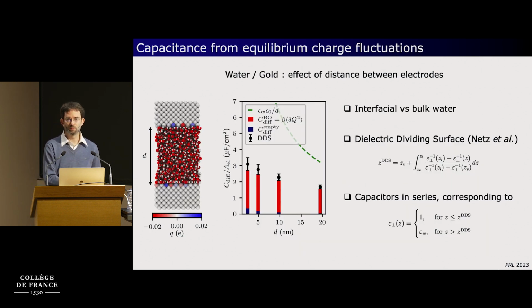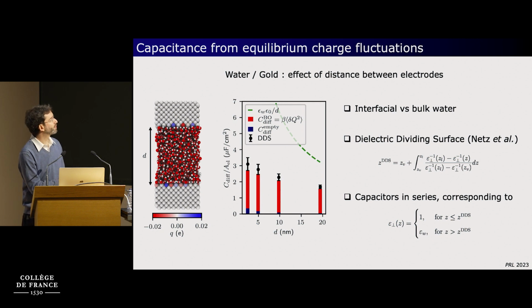More recently, we've moved to other types of capacitors. For example, one based on gold electrodes, model gold electrodes, and water molecules. And here is again the differential capacitance, now as a function of the distance between the two electrodes. And you see that it decreases. Don't worry about the details between red and blue, but the histograms are the results from molecular simulations. It decreases as you increase the distance between the electrodes, as predicted by continuum theory, which is the dashed green line. So the continuum theory tells you that it decays as 1 over the distance between the electrodes, with the permittivity here of the liquid. But in fact, you see that there is qualitatively the same decrease, but it's far off.